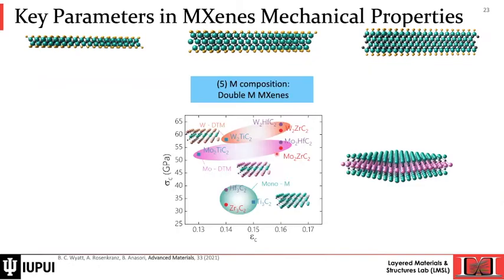Lastly, I talk about double transition metal MXene, the double M MXenes. Here we show that when we go from single or mono M MXene to double M, for example, if we have a Ti3C2 and we change the outer to molybdenum, we can have higher mechanical properties. And tungsten obviously would be the highest.